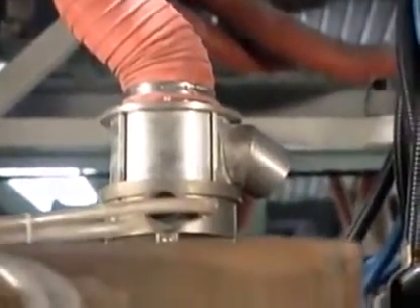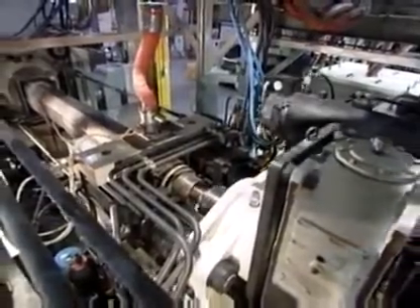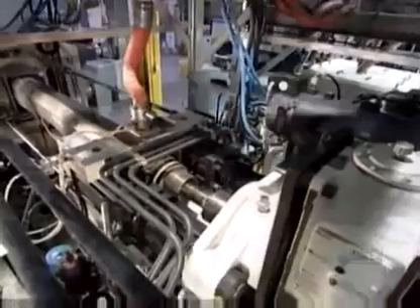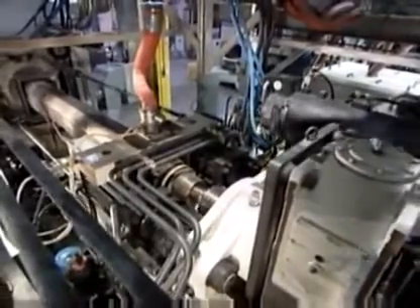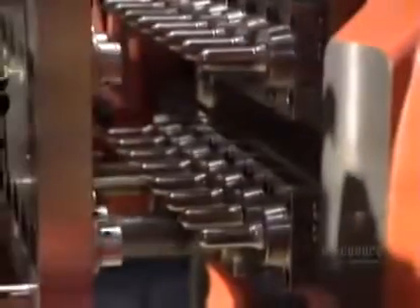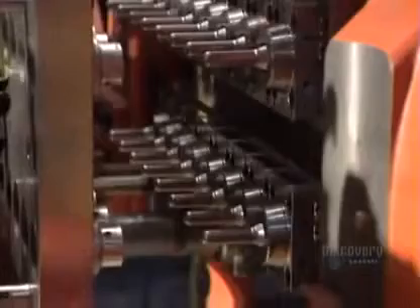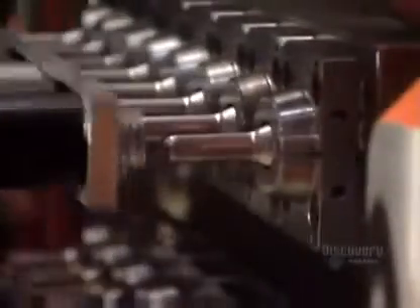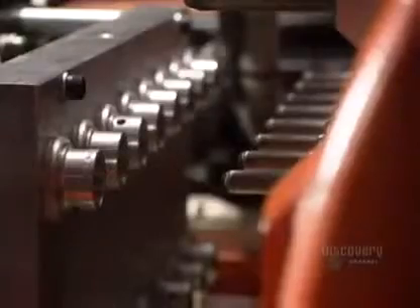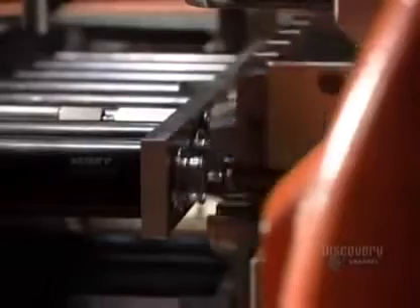The PET drops from the mixer into a plastic injection machine that heats it to a piping 315 degrees Celsius. The dry raw material melts into thick and gooey liquid plastic. The machine then shoots it at high pressure into a mold. This plastic injection molding process casts pieces of plastic called preforms, starter shapes that subsequent machines will transform into bottles or jars.